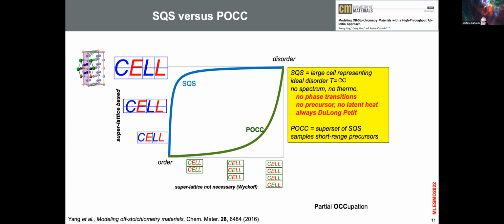So for an ideal disorder, these correlations are actually analytical. If you are at 50-50 composition, and one position is black with 50% probability and the other is white with 50% probability, then the correlation is 0.5 times 0.5, which is 0.25. For a ternary it is one half cubed. For a quaternary cluster it is 1/2 to the power of 4. This is if you are 50-50. If you want to go to different compositions, you can generate them all. But the message is that for the ideal disorder, the correlation of the clusters can be calculated analytically.